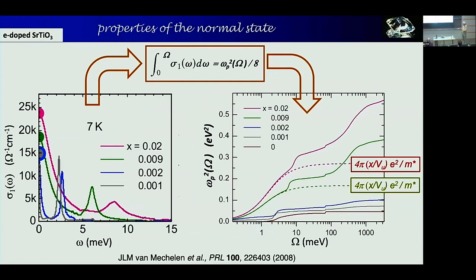It's very difficult for these materials, I can assure you. We had to make very thin plates and do transmission and also reflection, and so a combination of things that allowed us to determine these optical conductivity curves. And what you see here is the Drude peak at low frequency in this red curve, and then there is the phonon.